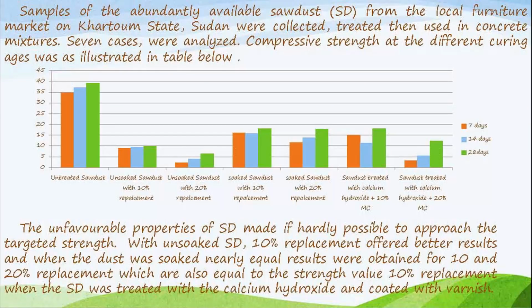The sample of sawdust is from the local furniture market in Khartoum State. Then we collected the sawdust, treated it, then used it in the concrete mix, 7 cases. We conducted the compressive strength tests for the 7 trials. We have some positive results for the treatment of using sawdust as replacement for fine aggregate.